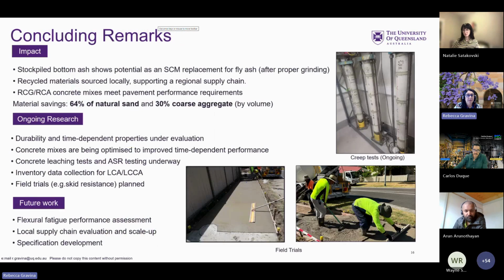I hope I've been able to provide a good overview of a testing or research framework to follow when trying to characterise recycled materials and optimise mix designs to fit particular performance requirements. And in terms of the impact that this work has, it shows that the stockpile bottom ash has potential as an SCM replacement for fly ash after proper grinding. Recycled materials are sourced locally, supporting a regional supply chain. Recycled crushed glass and recycled crushed aggregate concrete mixes have been developed that meet pavement performance requirements, and we've been able to have a material savings of 64% of natural sand and 30% of coarse aggregate by volume.